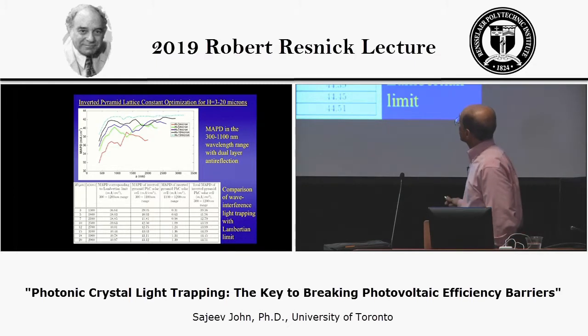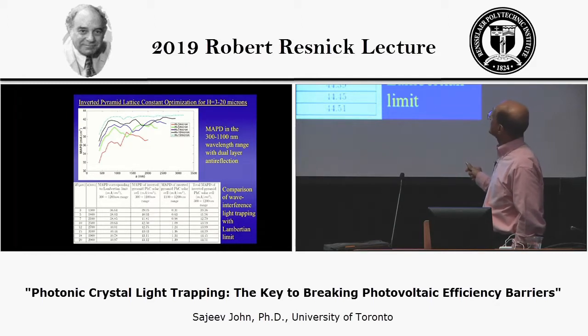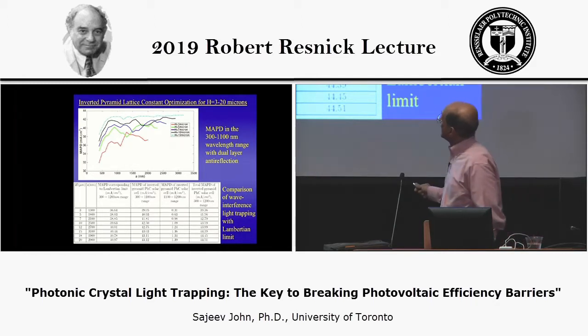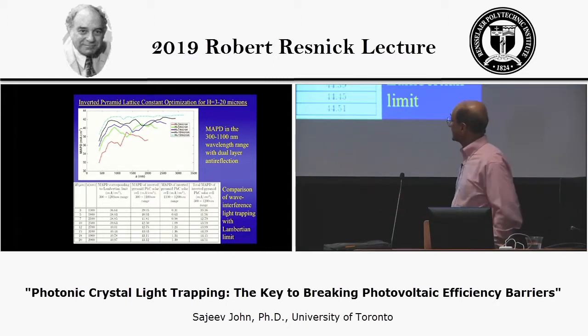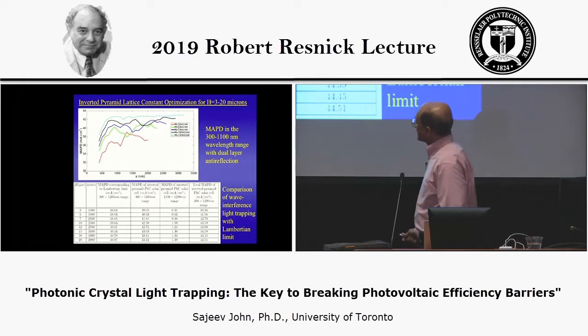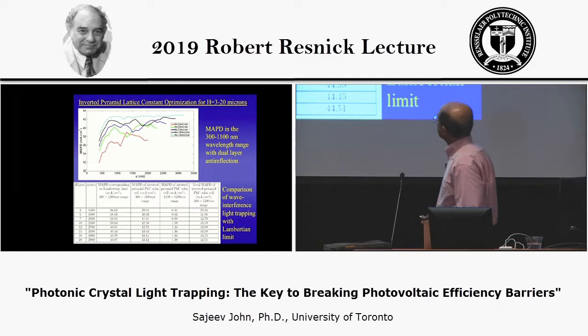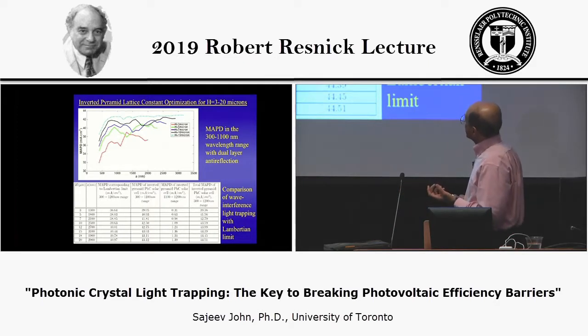And so here again are some calculations of different inverted pyramid structures of different thicknesses going from 3 microns up to 15 microns. And there's a lattice constant which optimizes the photocurrent density. And now we're talking about absorption over the entire 300 to 1200 nanometer range. And here it turns out that actually a 15 micron cell has the best result. This is showing the photocurrent obtained by Lambertian light trapping over the 300 to 1200 nanometer range. And in the inverted pyramid cell, you gain close to another milliamp in this 1100 to 1200 nanometer range.